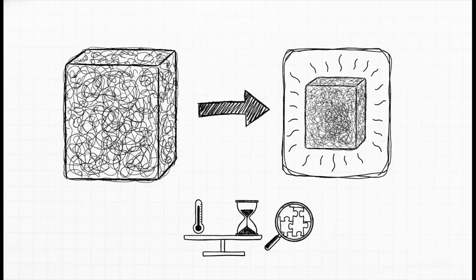And what's really wild here is the level of extreme precision required during that sintering phase. As that powder densifies into a solid block, the zirconia shrinks by a massive 20 to 25%. Engineers have to account for that shrinkage perfectly. But even more importantly, the exact temperature and the amount of time in the furnace dictate the final size of those microscopic grains. If it sits in the heat for too long, the grains grow too large. And if that happens, well, the grains might just spontaneously transform while cooling down, causing the whole piece to self-destruct. Or they'll lose their transformation-toughening superpower entirely. It is a crazy, delicate balancing act.